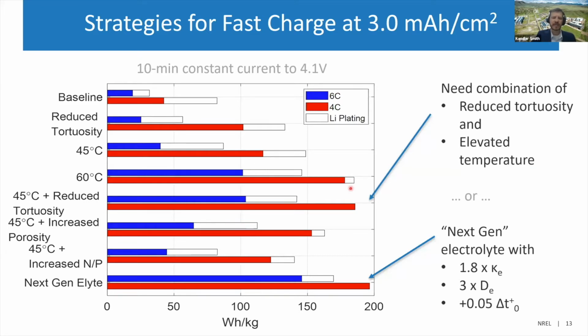And so really what we feel is necessary with present technology is to do a combination of reduced tortuosity. So this would be things like having secondary pore channels in your electrodes, or aligning the particles so that they stand up vertically in the electrode instead of laying flat in the electrode, as well as the elevated temperature. Or the best solution here would be to have some next generation electrolyte, which doesn't exist yet, and this is a tall order, but this is also a research effort under the Extreme Fast Charge program. And so Andrew has identified some requirements that you have to roughly double the conductivity, have about 3 times the diffusivity, and also modestly increase the transference number. So with that, we could have both energy dense, 10-minute fast charge capable batteries.